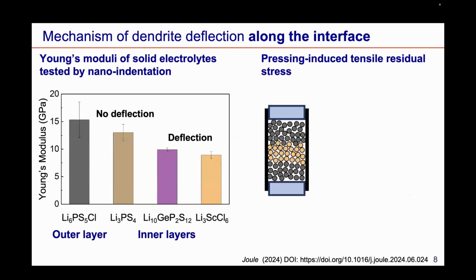The biggest difference between these different layers is their Young's modulus. We measure the Young's moduli of these materials by nanoindentation. There is a close match between the Young's moduli of the LPSC and LPS, which is consistent with the observation of no crack deflection along their interface. The Young's moduli of the LGPS and the lithium scandium chloride are notably lower than that of the LPSC. This elastic moduli difference may affect the interface strength when fabricating these multi-layered electrolytes, because these multi-layered solid electrolytes are formed by cold pressing their powders under a 400 megapascal pressure.